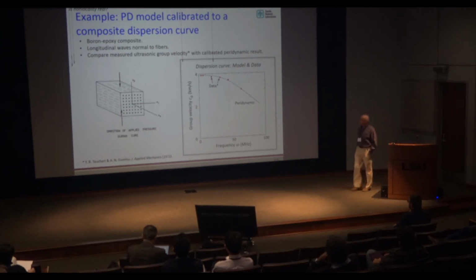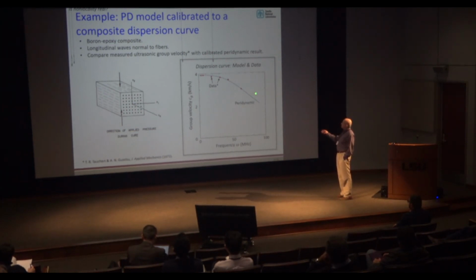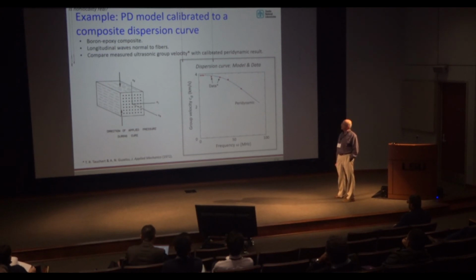I went through this exercise of calibrating a peridynamic micromodulus to measured dispersion data that was published. The material was a boron epoxy fiber reinforced composite. So I evaluated the micromodulus by inverting the Fourier transform of the dispersion curve. Then I took that micromodulus and computed the dispersion curve in the peridynamic model to try to confirm that it agrees with the same data that we started with, and indeed it does.